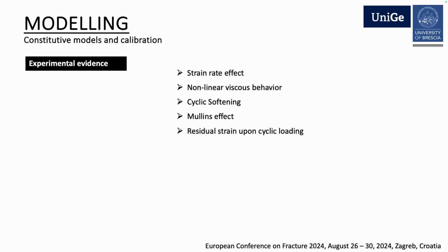So what we have gathered in terms of experimental evidence is that we have a complex material in which we have a strain rate sensitivity. We have a nonlinear viscous behavior. There is some cyclic softening, Mullins effect, and there is a residual strain upon cyclic loading. So our idea is to investigate whether viscoplastic models can actually model this type of response, taking into account that in the previous works, we have used simply a hyperelastic constitutive law.